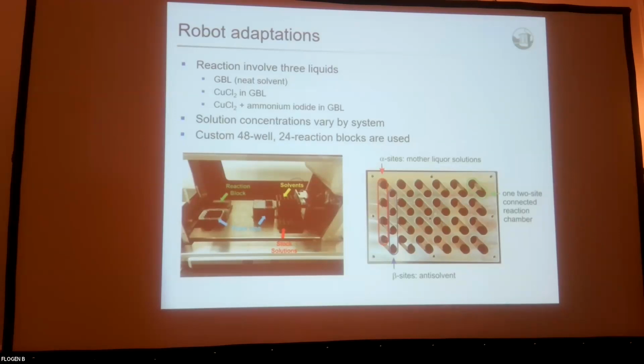This is the block that we designed. It's really based upon a 96 well plate. We just removed half of the wells, which enables us to isolate each 2 well reaction chamber separately from one another. So we have a 48 well block with 24 reaction chambers, so we can do 24 reactions in one shot. Again, it takes about an hour or so for the robot to fill this, and then we can allow these to sit on the robot deck, and so we can run many of these in parallel.